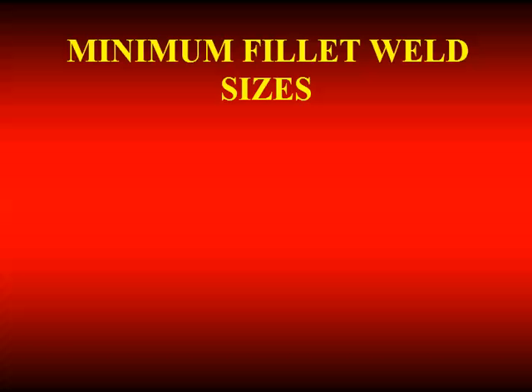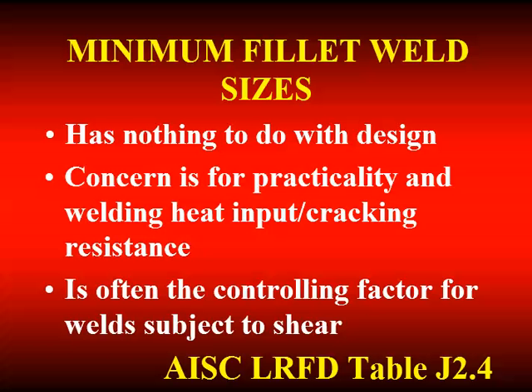Just as we had minimum PJP groove weld sizes, table J2.4 gives us minimum fillet weld sizes. Again, it has nothing to do with design. The concern, rather, is for the practicality of welding and to give us ample heat input to resist cracking. What's very important is that the minimum fillet weld size is often the controlling dimension when we do our weld calculations. So you go through and you make the calculations, the required weld size, and if it's a full-length joint, you often find that what you calculate is smaller than the minimum prescribed size as you see in table J2.4.